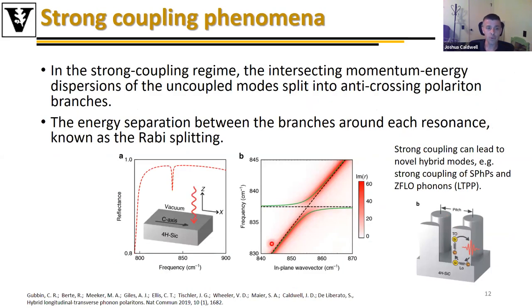So if I look at that in a simplified state here, this is in collaboration with both Stefan and Simone, you could see the phonon polariton mode would have a dispersion like this line here. The zone folded LO phonon is non-dispersive, should be flat here. But in this coupled case, what you actually find is that as the energy of this phonon polariton mode approaches that of this zone folded LO phonon, I end up with an anti-crossing between the two modes. This is the definition of a strong coupling between these two, where the strength of that coupling is dictated by the separation here, which is called the Rabi splitting.